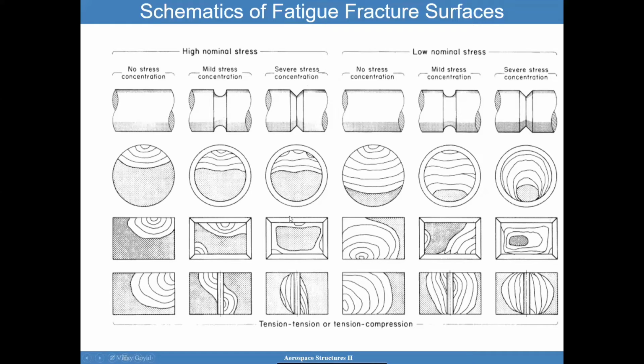If you have a severe stress concentration, multiple initiation points are possible, and then typically the failure surface will be towards the center, okay? And then I can keep going on. If you have lower stress concentration, more beach marks, more propagation with very little area left for it to fail. And that will be the case here too. A lot of initiation points, multiple initiation points. And then here you're going to have multiple initiation points, but with final fracture towards the center. So important considerations